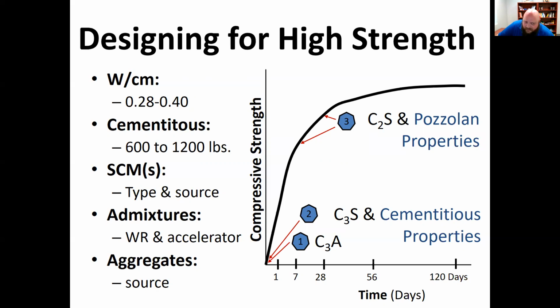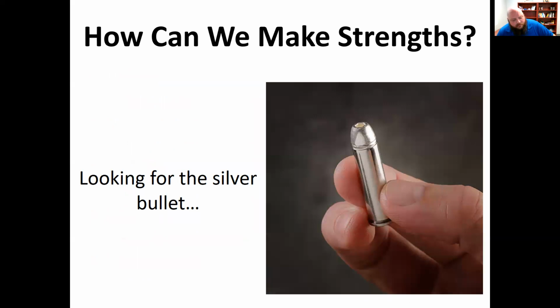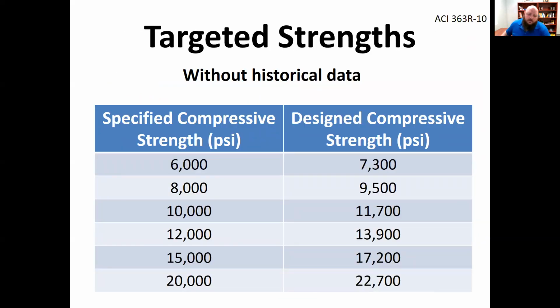Other things like accelerators and retarders can be used in different ways pretty effectively. Water reducers really improve that workability as you get lower and lower water cement ratios. And then you have your sources of aggregate and what your nominal maximum size is. Just to remind you, if you're trying to hit a certain target, you always want to have a safety above that. So here's some historical data to hit some of those targets. If you need to hit 10,000 psi at 28 days, your design compressive strength is going to be at least 11,700.